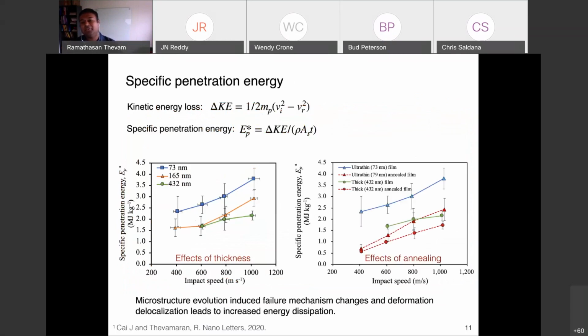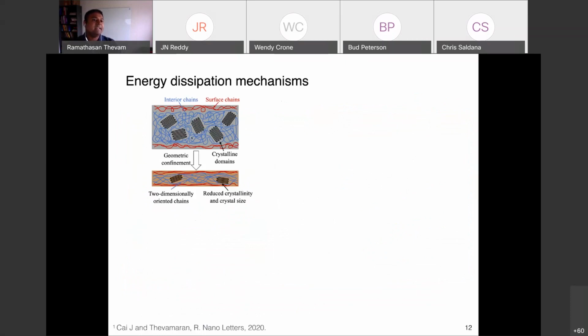And if you compare to the crystallinity, if you increase the crystallinity, regardless of the thickness, it reduces the specific penetration energy. So why did this happen? As I said, it is the geometric confinement. As you confine the thickness of the material, the crystalline domains will have a hard time forming, so you have reduced crystallinity. Also, these crystalline domains will align more laterally in the transverse direction. In addition to that, the polymer chain lengths are now comparable to the thickness of the material, so the entanglement morphology in the amorphous region will also change in the material.